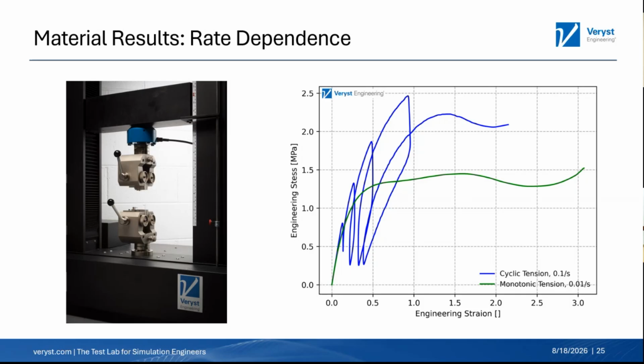Similarly, although we haven't really discussed it today, time and temperature are related in polymers. So we also see a lot of rate dependence at this rate, where we might not expect to see this much rate dependence, a 50 to 60% increase in the peak stress with an order of magnitude change in the strain rate. We might not expect to see that unless we're at one of these transition temperatures that Scott was just talking about.